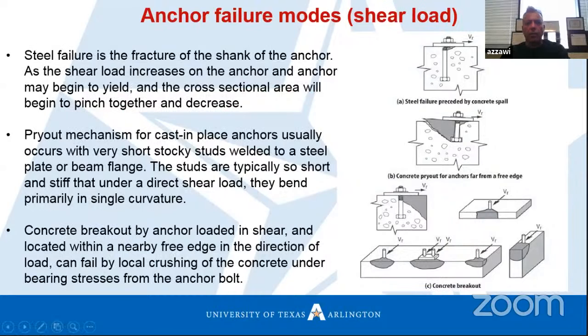This slide shows us the anchor failure modes for different types of behavior. First, we have steel failure preceded by concrete spall. If we apply shear at this anchor, we expect shear failure at the steel itself. Or we have concrete pryout of anchor far from the free edge, which is the common one. When the anchor bolt is close to the edge and we apply shear, we expect concrete breakout, as we see here. These are the three anchor failure modes.